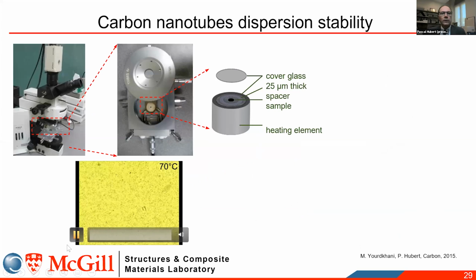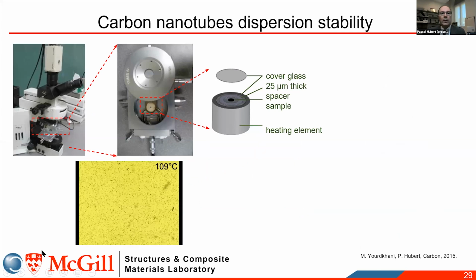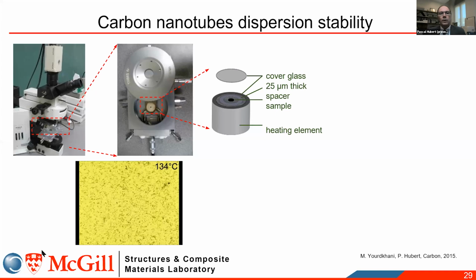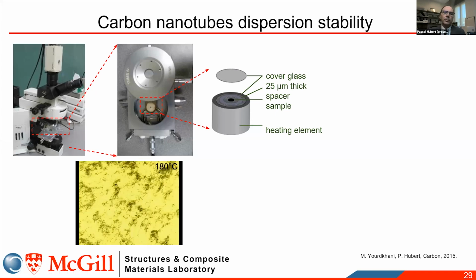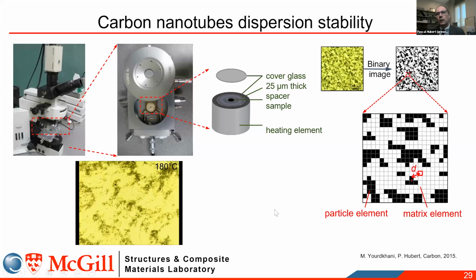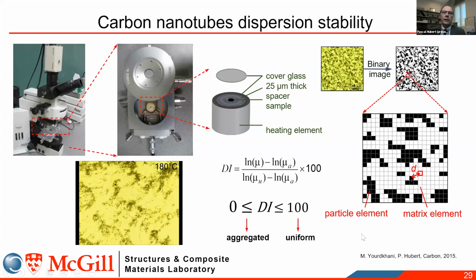And I'm showing here a little video where you're going to see the carbon nanotubes. As we increase temperature, they go from a nicely dispersed state to a not so well dispersed state, where you get agglomerates of the carbon nanotubes. And with these images, you can then do some image analysis. You can look at the distances between the matrix and particle elements and come up with a very simple index that will give you the quality of the dispersion, from a uniform dispersion to an aggregated dispersion.